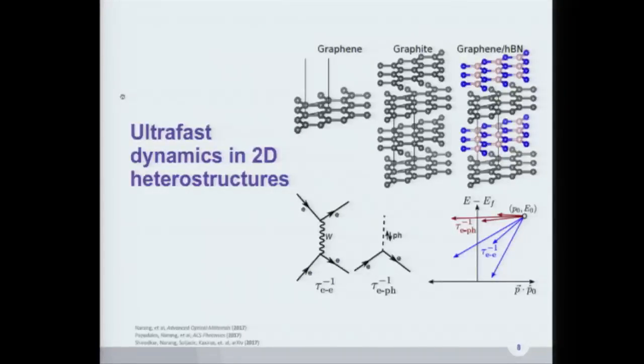We got into this by thinking about work in simple 2D heterostructures and including diagrams of this nature, so electron-electron scattering and electron-phonon scattering. And we looked at pretty simple cases, or things that I thought at the time would give us results that would be straightforward to calculate. So looking at a freestanding sheet of graphene, looking at graphite, which is another way of saying many sheets of graphene, but a slightly more conventional way of saying that, and also the graphene-HBN heterostructure.